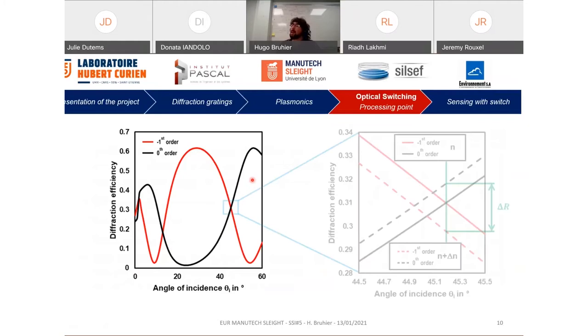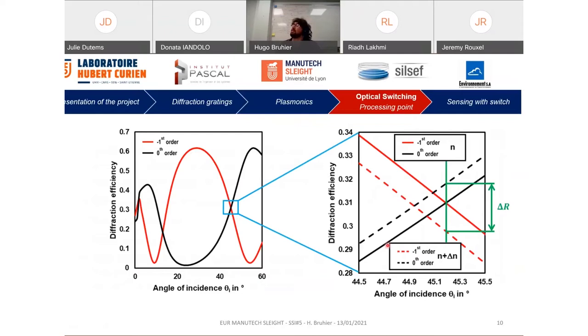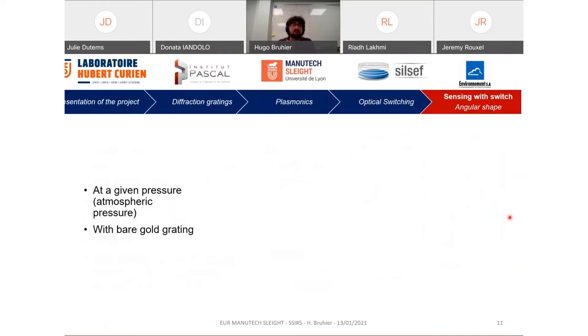So here is also another optical switching effect with another grating. And at this position, we have in plane curves the minus first order and fundamental order with a certain value of the refractive index. And by changing it, we have a displacement of this crossing point. But in our setup, we will not change our initial position. So we have a difference now between the energy of the minus first order and the fundamental order. So this quantity is our sensing signal. So now we will talk about experimental results.